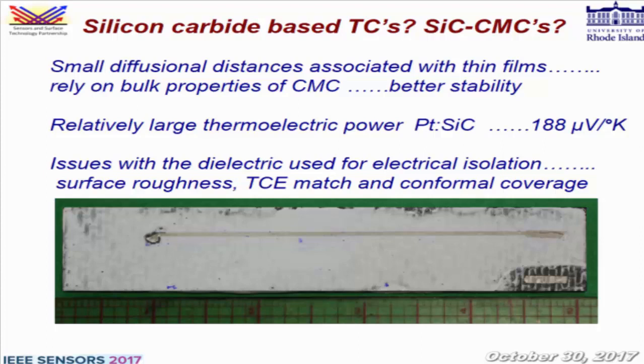Another reason why we leaned towards using this bulk material was that in literature, people had combined platinum with silicon carbide, monolithic silicon carbide, and achieved thermoelectric powers of 188 microvolts per degree K, which is large. So we wanted to replicate that. But with this approach, there were some issues.